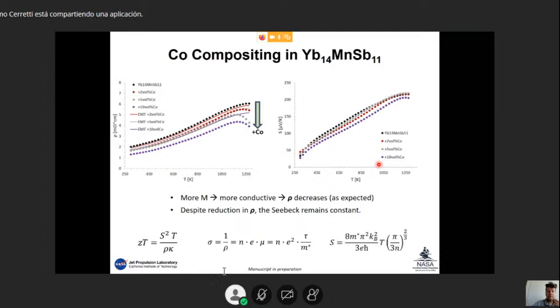So as we recall in the equation, generally when you have a reduction of the electrical resistivity, you should also have a reduction of the Seebeck coefficient. But what we observe instead is that the Seebeck coefficient was maintained constant at the same values of the pure 14-1-11, except for the 10% cobalt that showed a very minor decrease.